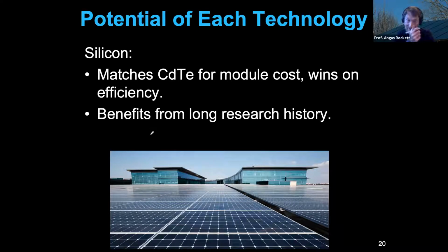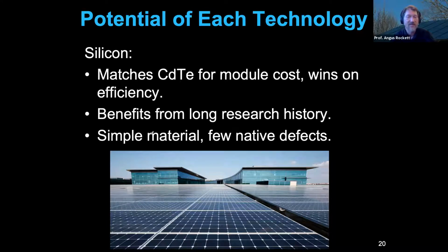And one of the things that's really clear about silicon is that it's a simple material with very few native defects. So you can have dislocations, you can have vacancies and things like that, but it's nothing like the compound semiconductors in terms of native defects. So it's a very easy material to work with, a very easy material to optimize. And when you have a problem, you can often turn to the rest of the literature to see what's going on.